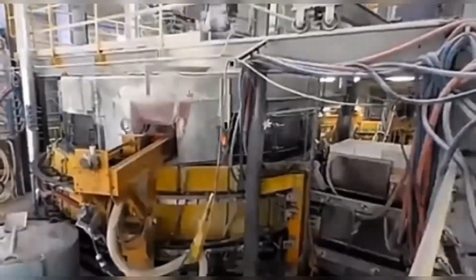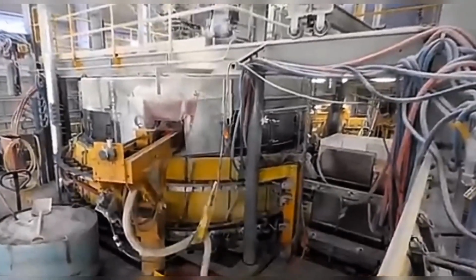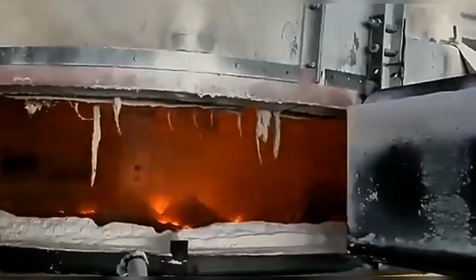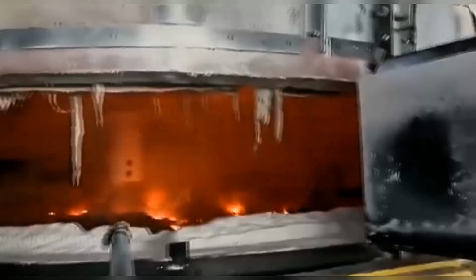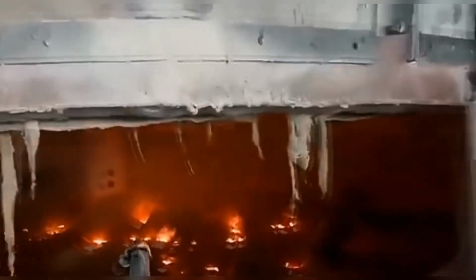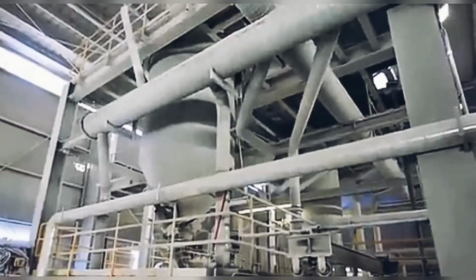Plants tune redox with small oxidizers or reducers such as nitrates and carbon to make fining efficient without discoloring the glass. Homogenization. Natural convection helps, but modern furnaces often use electric boosting, about 5 to 20% of total heat in some setups, and bubblers or stirrers to even out temperatures and composition, shorten refining times, and cut defects.